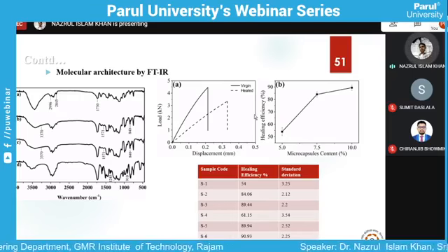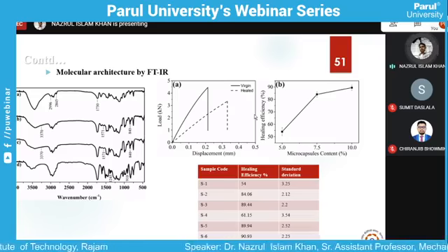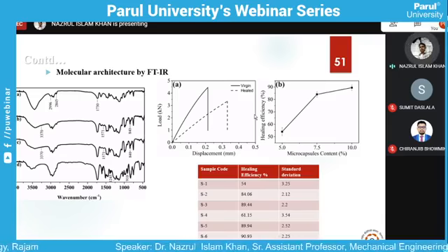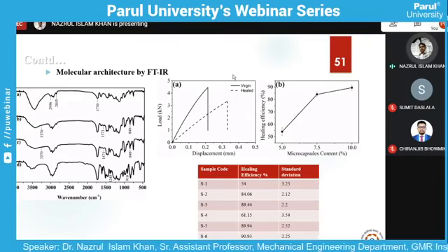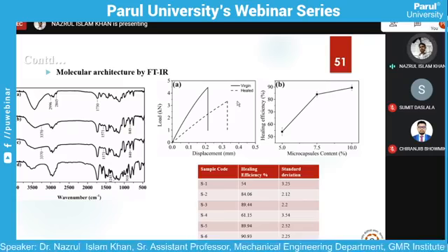So how did we calculate healing? First we tested the material until broken, and we recorded the interlaminar shear strength, ILSS, in case of the lap joint. Next, once we healed and tested again, we noted the ILSS after healing versus before healing. The ratio is the fraction to what extent it was able to recover the ILSS, and if you multiply by 100, that is the healing efficiency.